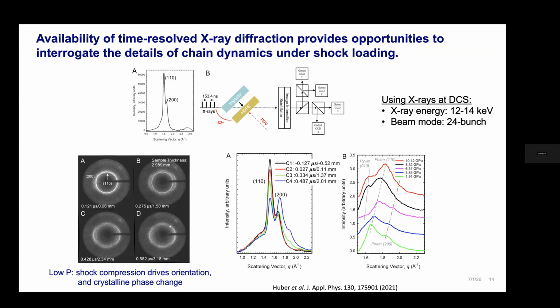One of the things that we wanted to do was actually look at some of these phase transitions using X-ray diffraction at the Dynamic Compression Sector. This is work in collaboration with Rachel Huber at Los Alamos. So with the coming online of DCS, we could get real-time, time-resolved X-ray diffraction of our polymer as we were shocking it. What is shown here are some of the detector images of polyethylene shocked to different conditions, and then I show the diffraction patterns down on the lower right.